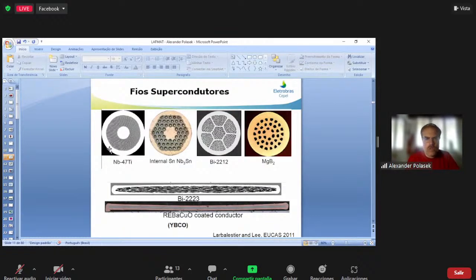Here are some examples of superconductor wires. You can see niobium-based low-temperature superconductors, magnesium diboride, BSCCO-based wire, and rare earth YBCO-coated conductor. And you can see that all these materials have a metallic, non-superconducting matrix with a multifilamentary architecture, where each filament is superconducting.